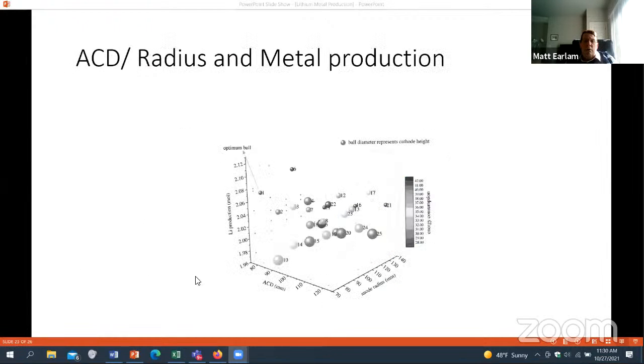So the people at the University of London have actually done some modeling of this process, and what they looked at was changing the anode cathode gap. Here it is in millimeters, and then the anode radius, here it is in millimeters, and then the lithium production rate in terms of moles per hour, which is their use, but it actually correlates to kilowatt hours per kilogram, which is what you really want to be interested in. What they found is if you can minimize the gap to about 80 or so millimeters and keep the anode smaller rather than bigger, then your maximum production rate curve is about here and then about here. So that was kind of interesting.